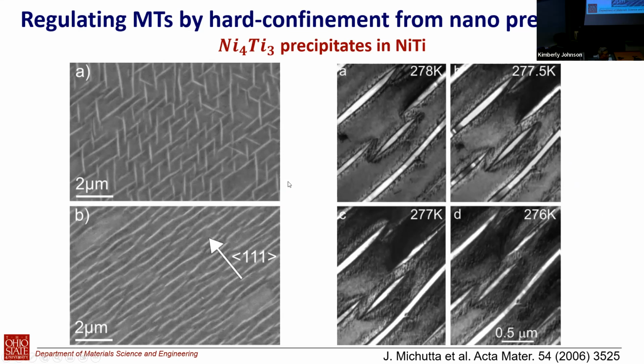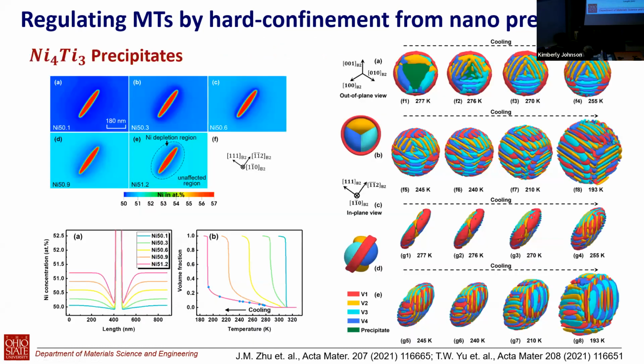You can control the aging time, the aging temperature, and also the aging stress. You can create different sizes and different spatial distributions of this precipitate microstructure. Experimentally, people have seen that for these precipitates, you can induce R-phase martensite, which coats the precipitate. So that's the embryos of martensite, ready to go. When you apply a load, those martensite are going to grow. That's the experimental evidence.